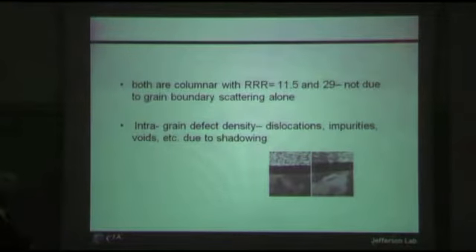In the sputtering case, since the deposition energy is so low for the condensing film, for a high melting point metal like niobium with a very low substrate over melting point temperature ratio, the predominant source of electron scattering defects that you would expect, both from simulation and from very extensive literature, would be dislocations, voids, and of course impurities. The structure of films deposited for any metal on a low temperature substrate is very poor for a high melting point metal.